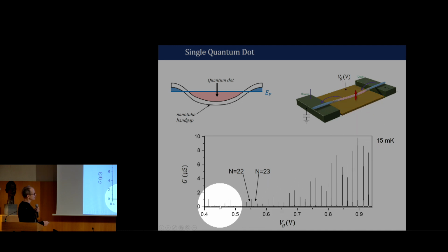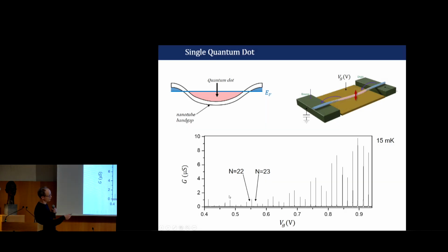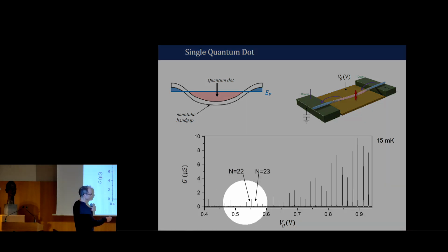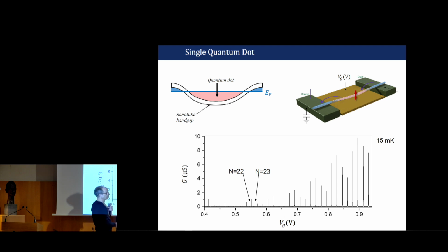And you see a series of peaks. So we work at very low temperature. We work at 15 millikelvin. And in between two peaks, here, we have a constant number of electrons. And in this case, we have 22 electrons in the nanotube quantum dot, and the separation between two peaks in the conductance is given by the Coulomb energy that you have to pay to add one electron in the quantum dot.